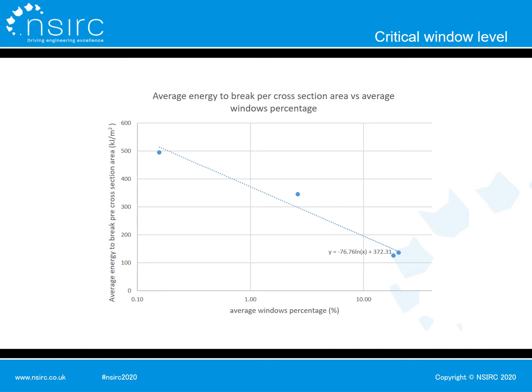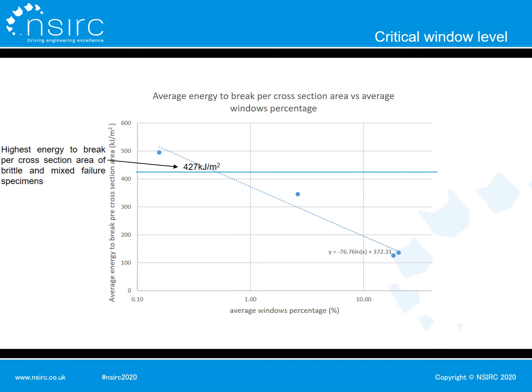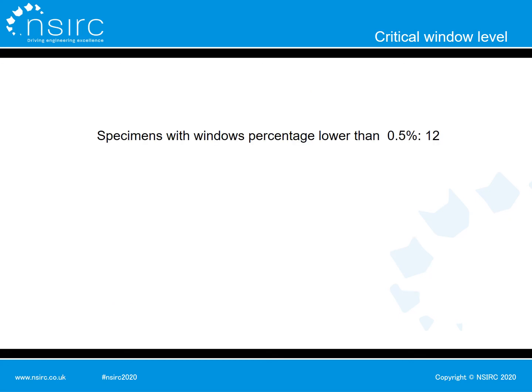To find the critical level of windows, which does not affect the joint integrity, the average energy to break per cross-sectional area of each pipe side was plotted against the log average window percentage of each pipe side. The highest energy to break per cross-sectional area of the specimens fractured in brittle and mixed mode was selected as the critical energy level. Then the corresponding window percentage in this plot is 0.5%. There are 12 tensile specimens with window percentage lower than 0.5%. 11 of them fractured in ductile mode, only 1 specimen fractured in the mixed mode, so this indicates that 0.5% is a reliable critical window level.